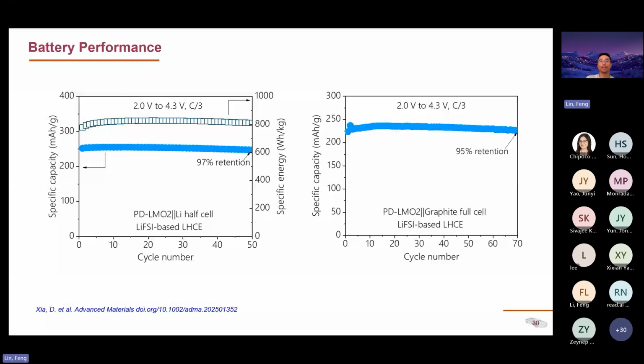how we can simplify the materials making by taking existing commercial material, perform a mechanical milling to create disorder in the cathode, and meanwhile creating carbon coating to help with the conductivity. We still have a long way to go, but I think this elemental simplicity without going for complicated doping, without going for a complicated synthetic process, just through a dry mixing step, using mechanical milling could be a great pathway for the cathode making. And manganese obviously is much lower cost and much more available compared to nickel and cobalt.